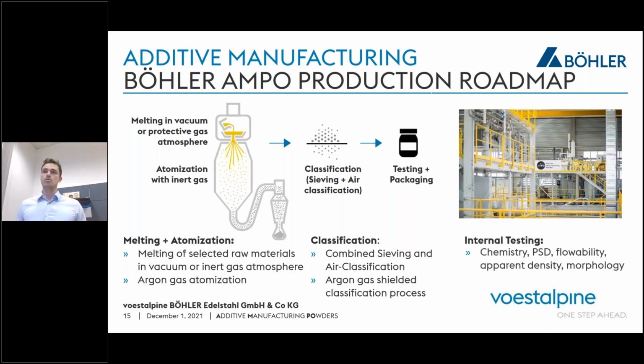And we also do, of course, after every batch, internal testing where we test the chemistry, the PSD, which is the particle size distribution, the flowability, apparent density, morphology, and so on.